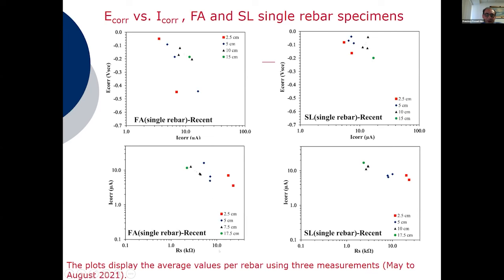Interestingly, at the bottom is the RS versus I-corr. In some cases, in these particular single rebar specimens, the RS that was measured, the solution resistance, was significantly larger for the smaller solution reservoirs compared to those from the previous page.